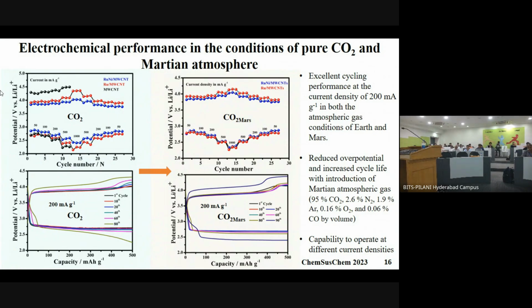When we go to the Martian atmosphere, the performance improves further, and there is a reason: some additional gases in the simulated Martian atmosphere rather help the system. The presence of a minor amount of CO helps the reversibility. So in CO2 Mars, we can see the overpotential is further minimized, and of course the ruthenium nickel system works better than the ruthenium-only system. Here we are able to achieve up to 93 cycles. So we see a reduced overpotential and increased cycle life with the Martian atmosphere as compared to pure CO2. What we also see is that, even within the CO2 system, the overpotential is less with the ruthenium nickel multi-wall CNT system.